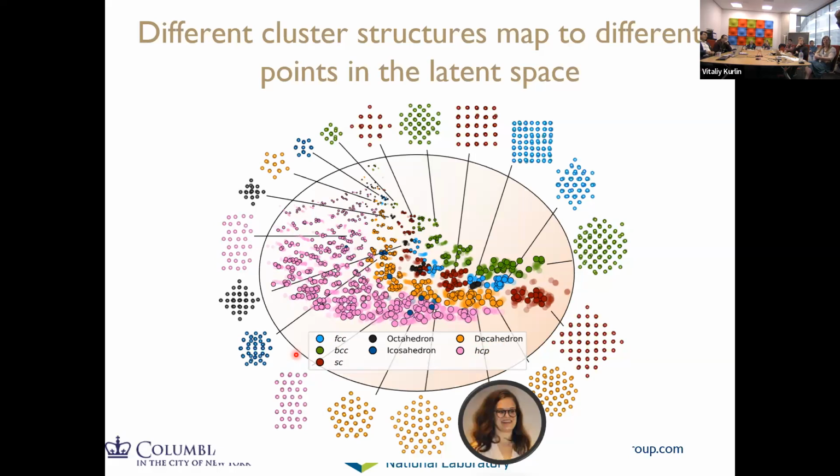And then I can completely interpolate from FCC to HCP, which makes this very perfect, because what I'm going to do is pick a point on my latent space, which interpolates from one that I know to another that I know, and it has at least a fighting chance to decode it correctly. So it worked brilliantly. And these decahedral ones are basically little chunks of FCC with these twin boundaries, and the twin boundaries turn out to be little tiny chunks of HCP. And so they should appear in between the HCP and the FCC. I know that's maybe too much information, but